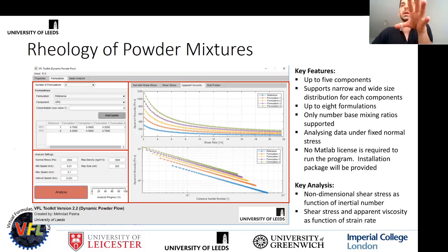So this toolkit would help in early stage formulation product development, where you can identify the bad formulation from the good one. That gives you the operational window of how much of what should be your mixture ratio between the components in order to get good flowability. For example, if you're having a screw conveyor, then what type of mixture, or how much of the free flowing component you need to add to the mixture in order to process the formulation.